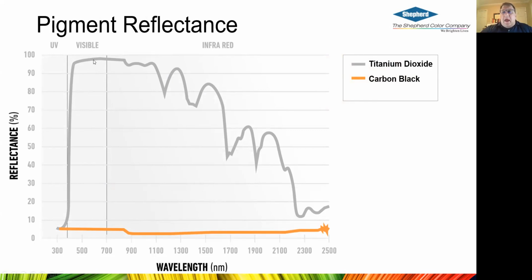So the titanium dioxide, in a plastic or a paint, will have around 80% reflectance. Meanwhile, a carbon black or standard black will have about 5% reflectance in the visible and all the way in the infrared. So it has around a 5% TSR.